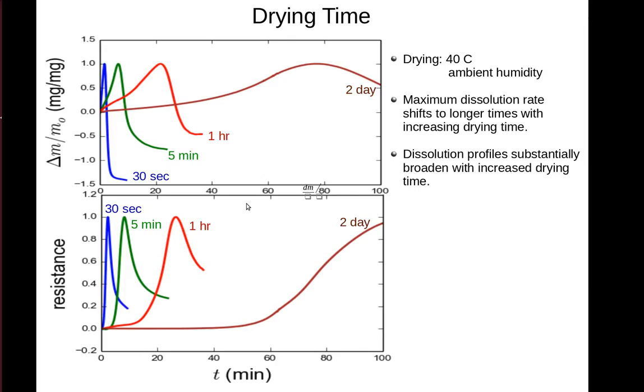We can study this more accurately using the QCM. Again, mass versus time, this time for films dried for different amounts of time: 30 seconds, 5 minutes, 1 hour, and 2 days. The plot clearly shows that as the film is dried for a longer period of time, it takes longer for the polymer film to dissolve at the same conditions. The resistance curve shows a very similar effect.